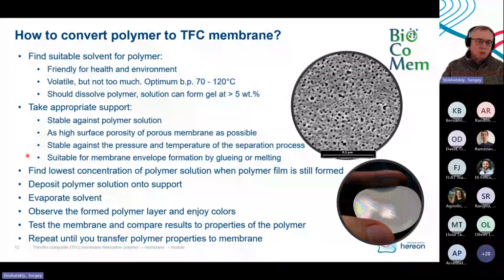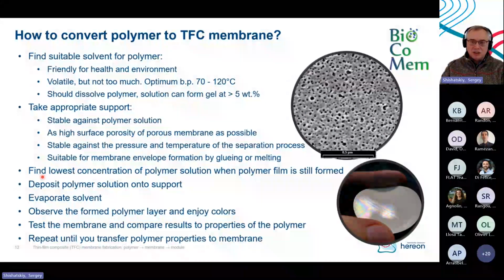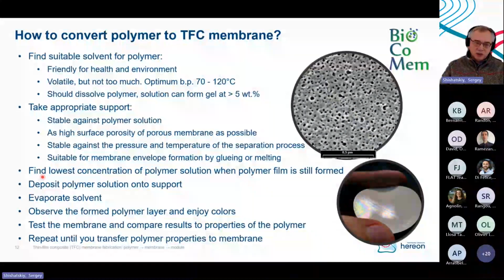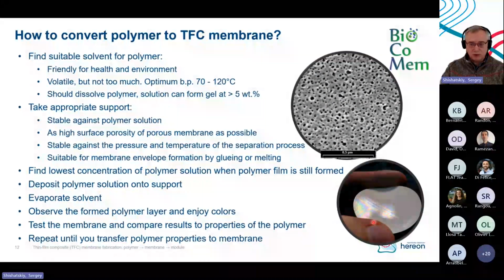Then we move to the next step, and we find the lowest concentration of a polymer solution where a polymer film is formed on top of the support which we are using. Then you deposit this polymer solution on the support, you evaporate the solvent, and then you observe nice colors which the polymer layer gives you on the surface of the membrane. If you don't see colors, your membrane is too thick, or the selective layer is too thick.